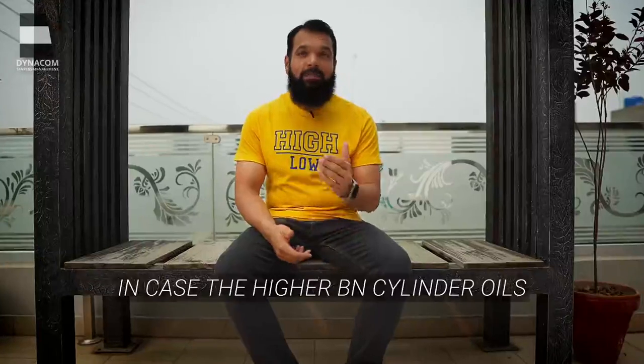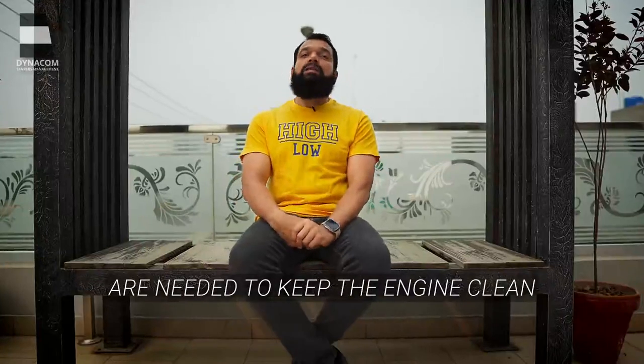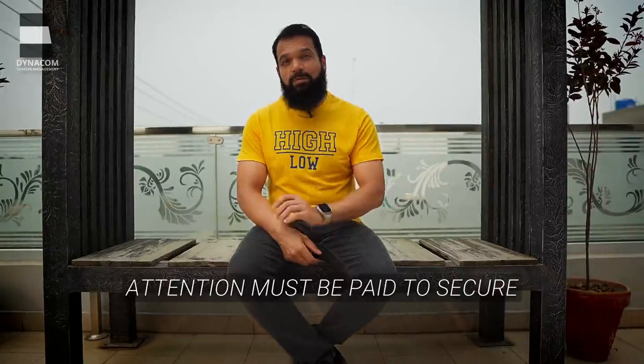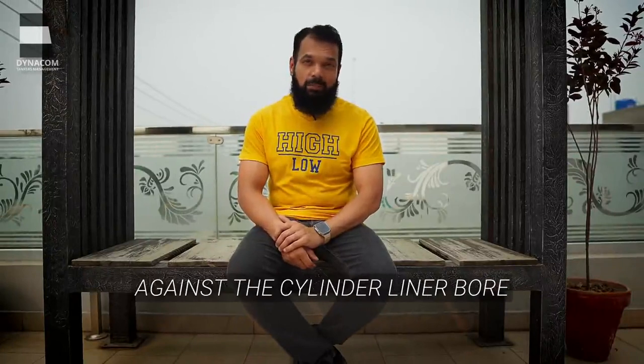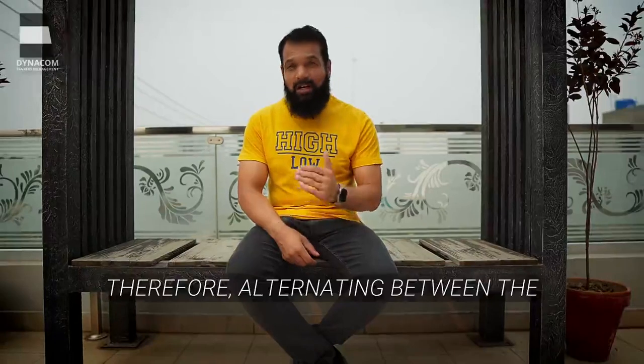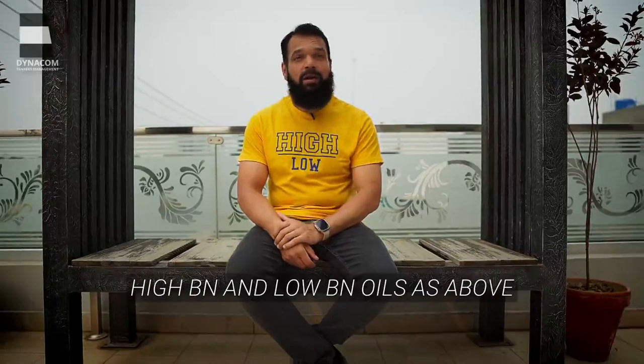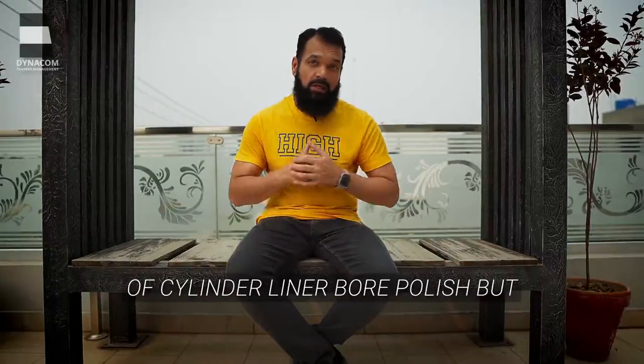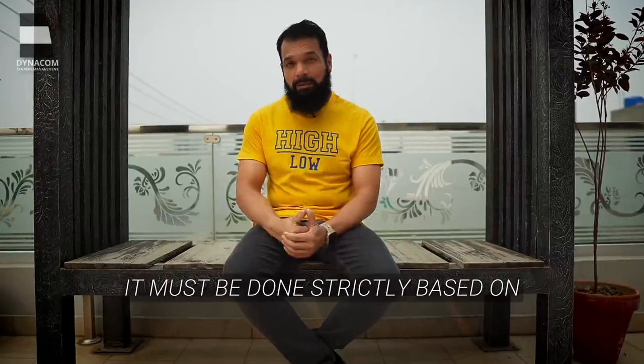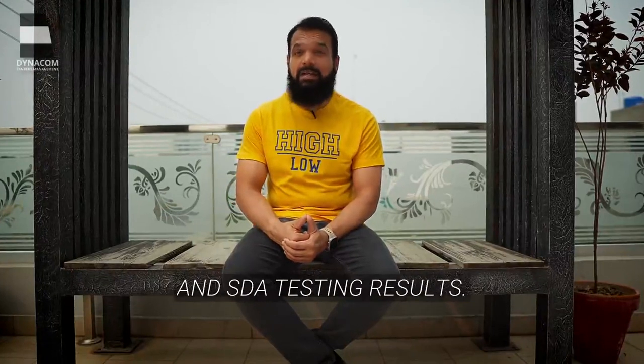In case the higher BN cylinder oils are needed to keep the engine clean from the deposits, attention must be paid to secure against the cylinder liner bore polish when engine running on VLSFO. Therefore, alternating between the high BN and low BN oils as above can reduce the risk of cylinder liner bore polish, but it must be done strictly basis under piston inspection and SDA testing results.